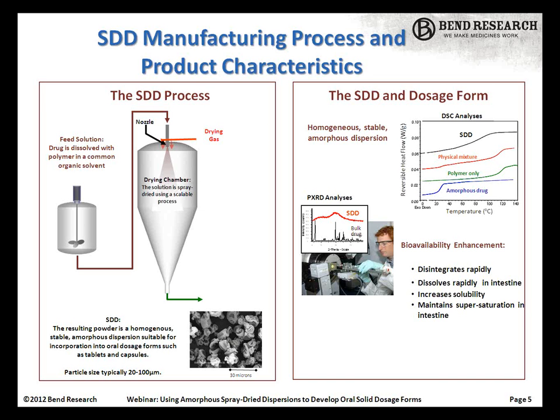So the process for developing a spray-dried dispersion involves taking your API and dissolving it in an appropriate solvent along with your selected polymer. What that does is allow you to break up the crystalline lattice forces by dissolving it. And then you spray dry the material, flash removing the solvent, which allows you to set the amorphous state within the dispersion.